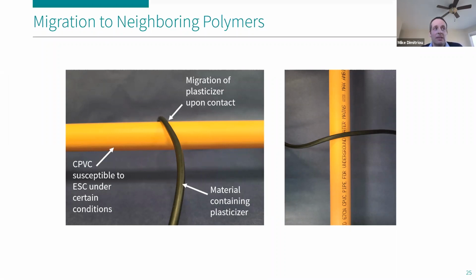Now, it turns out CPVC is susceptible to a form of cracking referred to as environmental stress cracking. This is a cracking that requires two components or actions to cause the material to crack. One is stress. It needs to be under some form of pressure from the water source or bending from some other external push-pull mechanism. And it also needs to be exposed to some type of solvent that could be a plasticizer. So under certain conditions, this is a scenario where you may in fact end up with plasticizer going into the CPVC and initiating some form of environmental stress cracking.